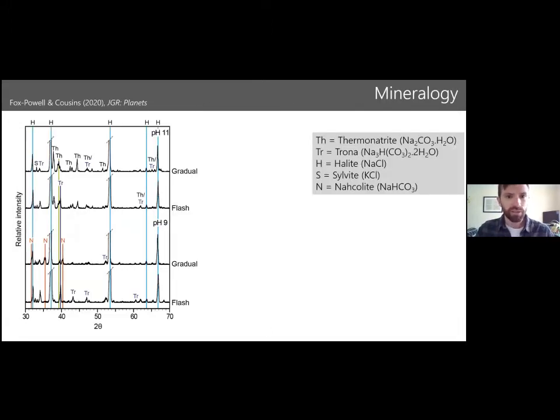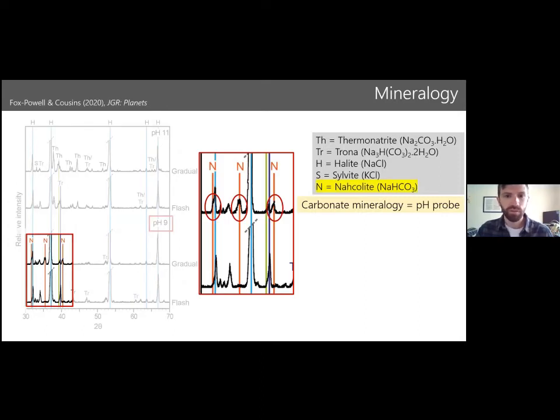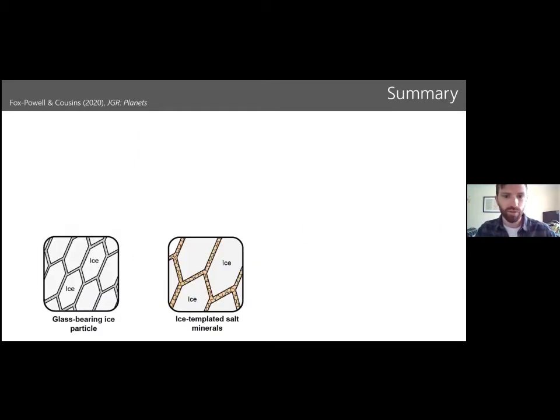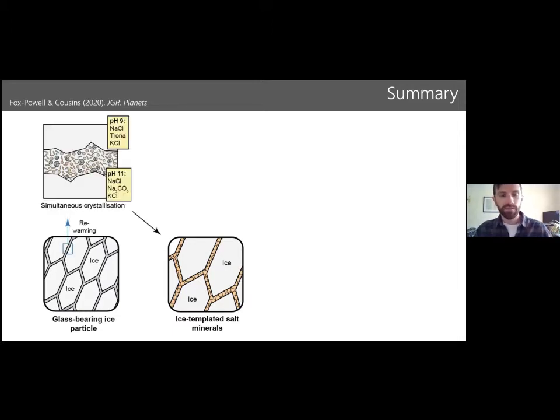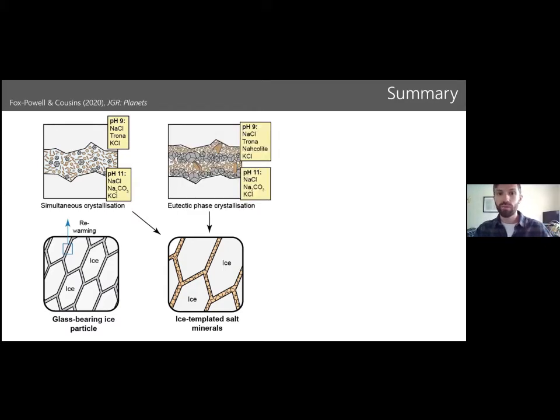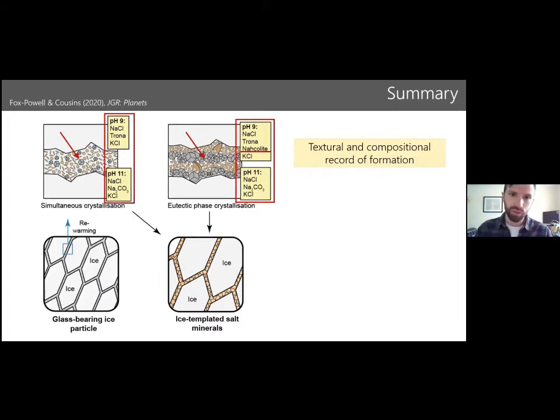We also looked at the bulk mineralogy of the particles and of the salts formed through these two routes, and found that there are pH dependent differences and also some signatures of the flash freezing, some kinetic inhibition of certain minerals, particularly in the carbonates, but I won't labor on that point. So to summarize that study, we found that there were two end member products of cryovolcanism. We either could have ice templated glass within the particle, or we could have salt minerals forming within those brine veins, again, templated by ice crystal formation. In the latter case, that can form through either simultaneous crystallization through the rewarming of previously flash frozen fluids, or it can form through gradual crystallization in sequence. And these two routes have both a textural and a compositional record of their formation. So we should be able to use mineralogy and texture to infer some of these dynamics indirectly.